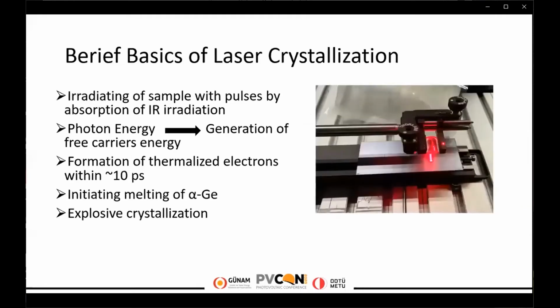Let me give you the brief basics of laser crystallization. The laser crystallization process via nanosecond pulse infrared laser is initiated with the melting of the amorphous germanium film by absorption of infrared irradiation. The interaction between thin film and irradiation initiates with the generation of free carriers and phonons through absorption of light by valence electrons, where electron-hole pairs recombine through non-radiative recombination and transfer the energy to the bulk atoms in the form of heat.